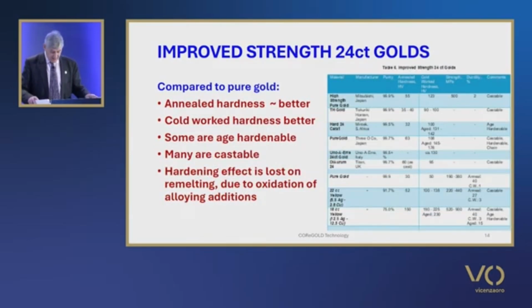So let's move on and just recap on improved strength 24-karat golds. As I reported in 2005, a number of improved strength 24-karat golds have been developed, some commercially available, and jewellery produced in these materials is in the marketplace, particularly in Japan. All have virtually the same melting point, colour and density as normal pure gold. These are listed on the table on the slide. It is evident from this table that while annealed hardness is usefully higher than for normal commercial pure gold, cold working results in significant hardness increases, and that some materials can be further hardened by low temperature aging heat treatments.